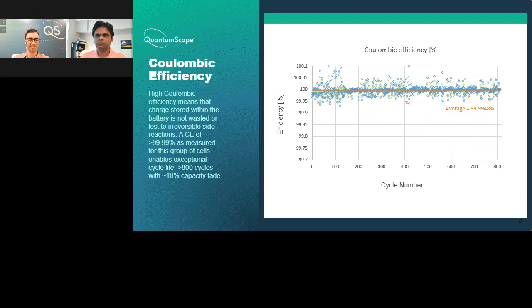So high coulombic efficiency is necessary. Another way to think about this is, suppose the coulombic efficiency of your battery were 99% and you didn't have any excess lithium foil, which Venkat said is expensive and occupies a lot of volume. So if you have no excess lithium foil and a 99% coulombic efficiency, you might think, wow, 99 sounds pretty good. That's almost 100, right? But a 99% coulombic efficiency would result in your battery being dead within about 23 cycles, if you use that definition that I described before as end of life at 80% of capacity. So even 99% coulombic efficiency is far from good enough.